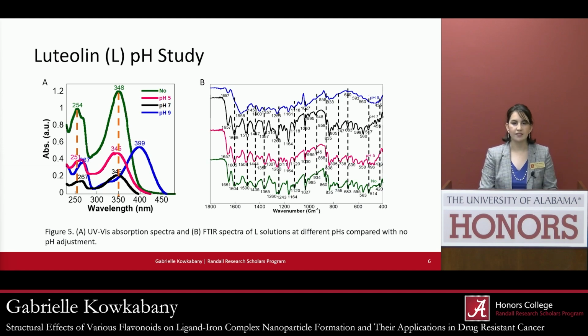And what I found for luteolin is that it has two distinct absorption bands at 254 and 348, which is consistent with literature values. But when the pH was increased to 5, there was a slight shift in this absorption, which indicates possible deprotonation. But then at a pH of 7 and pH of 9, there were further shifts which indicate the formation of degradation products. And this was confirmed with the FTIR spectra that I ran. And so at 3,400 wave numbers, there was a broadening that occurred, and additionally, from the 1600 range to the 1700 range, there were additional peaks that indicate the formation of carboxylic acid groups, which are found in degradation products of luteolin.